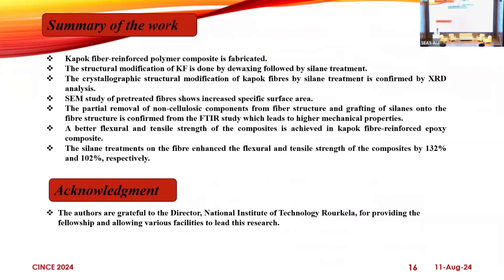This is the summary of my work, where kapok fiber reinforced composites are fabricated using the hand layup technique. The structural modifications are observed through XRD, FTIR, and FESEM, and we obtained that the silane treatment enhances the flexural strength by 132% and the tensile strength by 102% respectively.